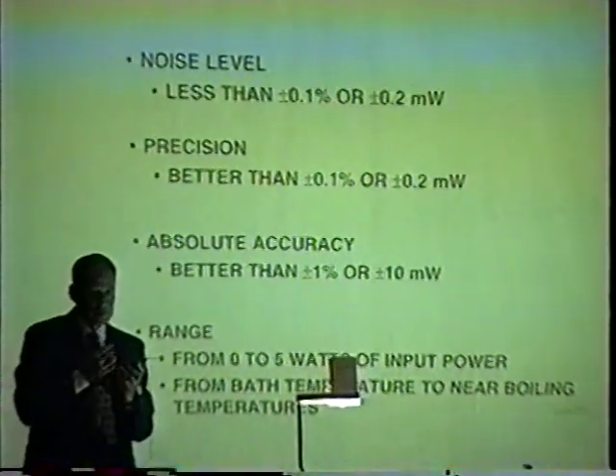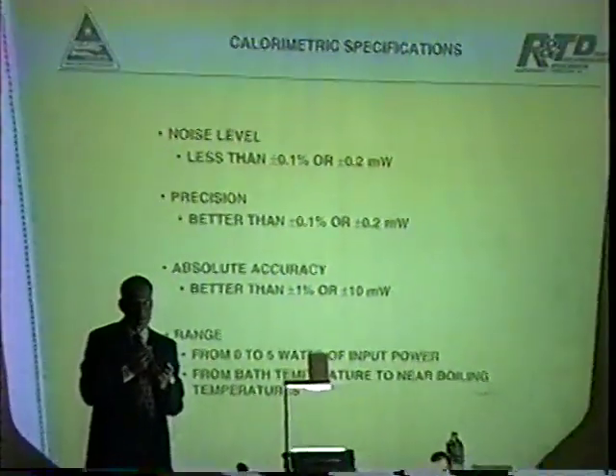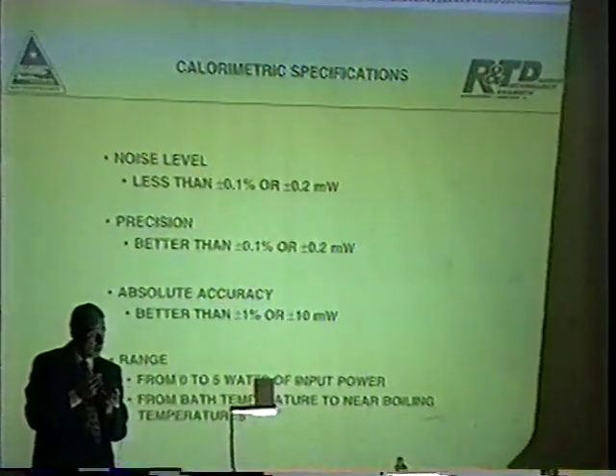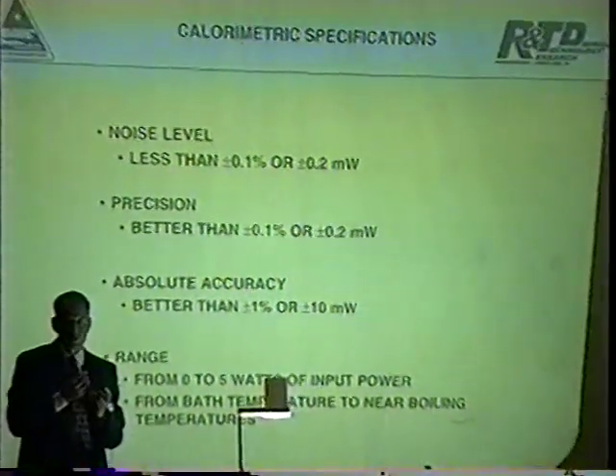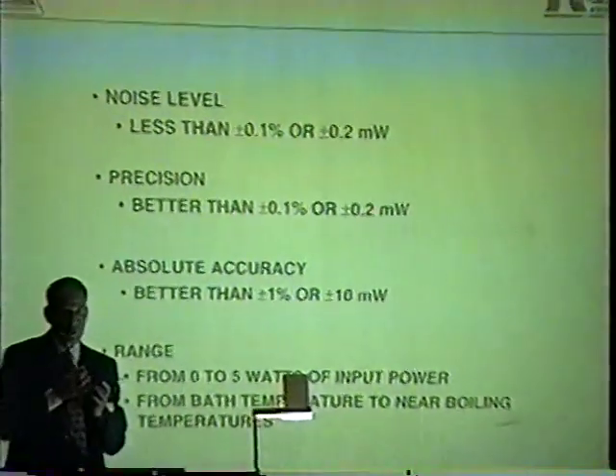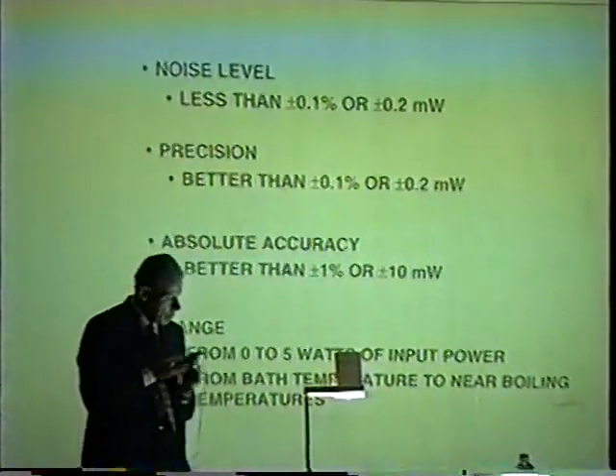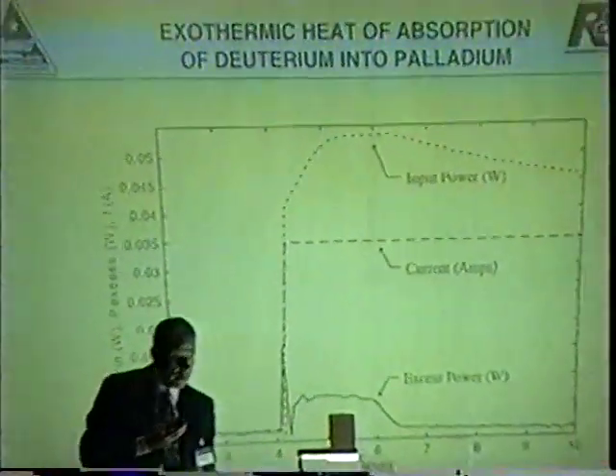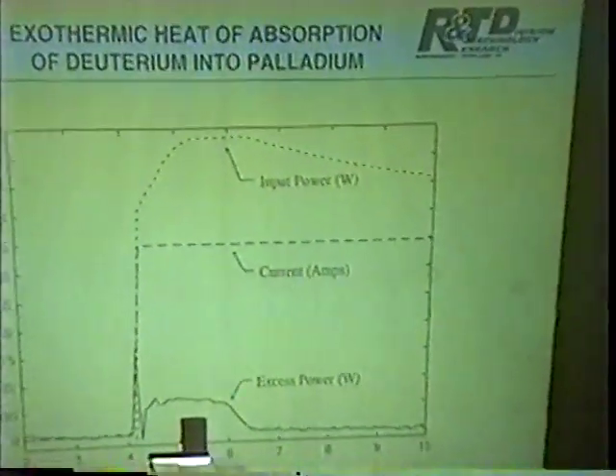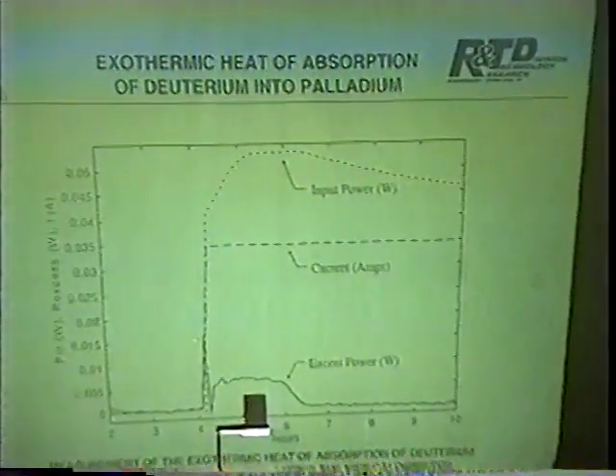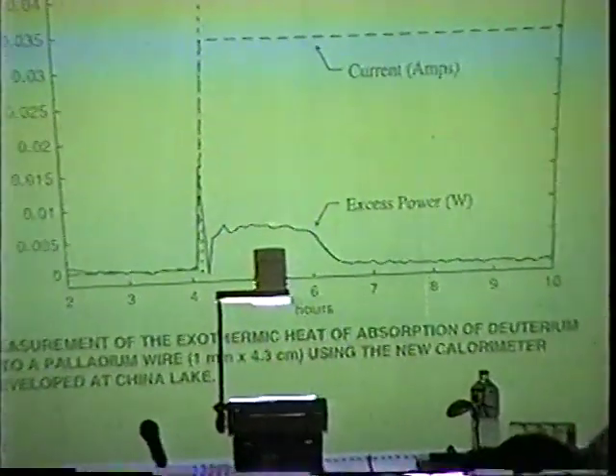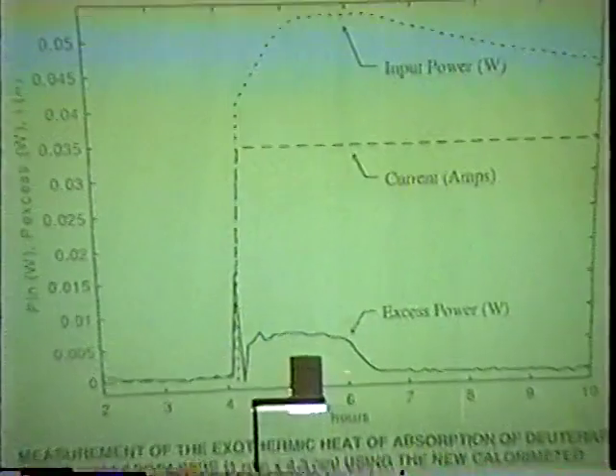We were able to get the noise level down measured within plus or minus 0.1%, where I've been measuring to plus or minus 1%, and plus or minus 0.2 milliwatts, where I've been measuring plus or minus 20 milliwatts. So basically a factor of 10 improved. And I particularly want to point this out. This shows when we turn the current on, this is the current here, this is excess power, we do see the heat of absorption of deuterium into the palladium.